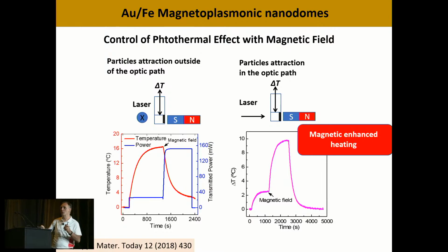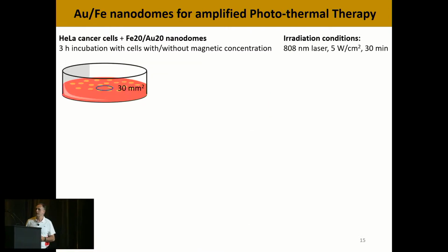And then if we do the other way around, now the laser is going in the same direction as the magnetic field, so now we concentrate our particles in the optical path. In this way, the heating in the beginning is small, then we put the magnet on, and we increase the heating considerably just by concentrating the particles in the optical path. So we can have magnetic enhanced heating using this simple approach. Then we used this to try in vivo.